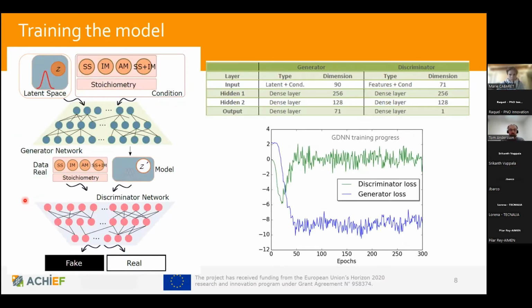So basically this kind of adversarial neural network is used, where we have this generator and then this discriminator, and they are trained so that the generator will generate candidates that this discriminator can no longer describe to be fake. So basically we would come up with this real-like alloys or real-like candidates. These neural networks both have two hidden layers, and as said, these parameters that were mentioned before are used. This needs to be quite fast, so basically these training epochs or training cycles don't need to be that many. So in that sense, this seems to be quite fast to train.